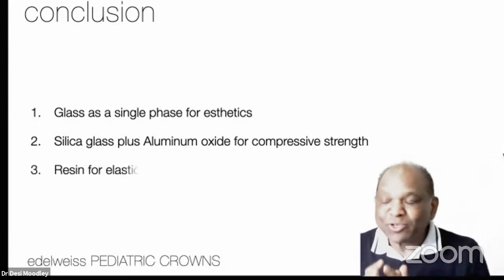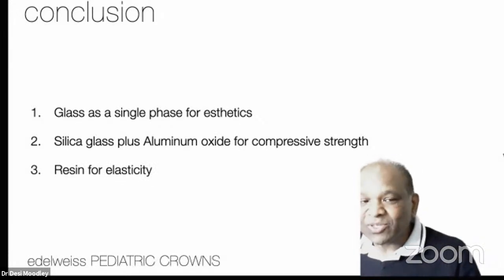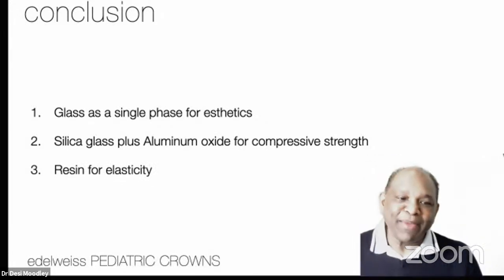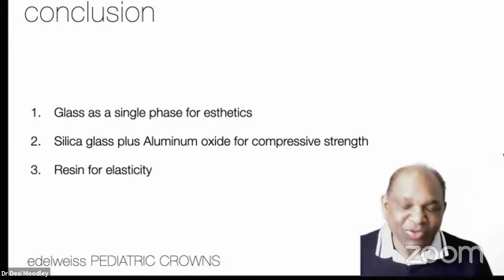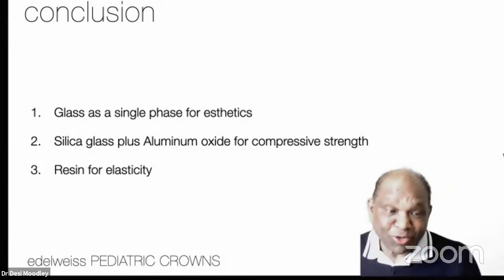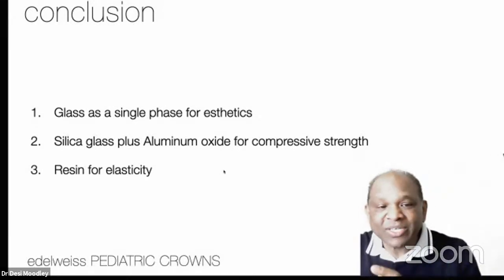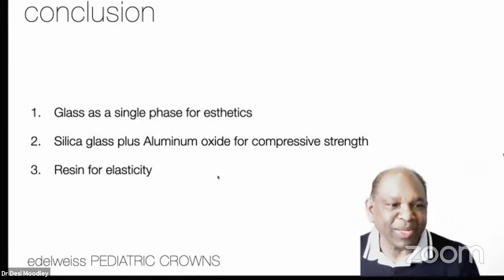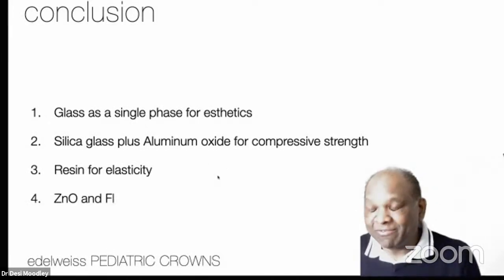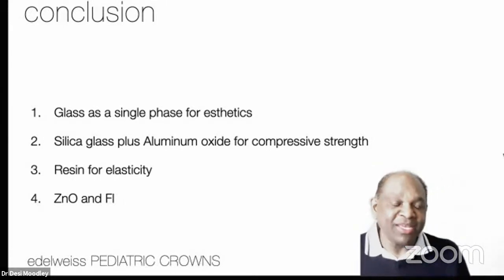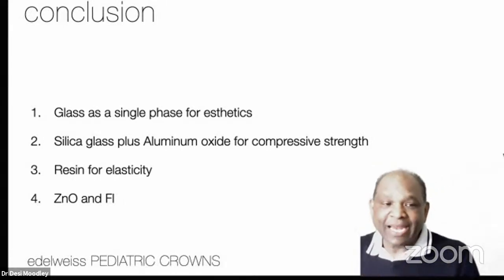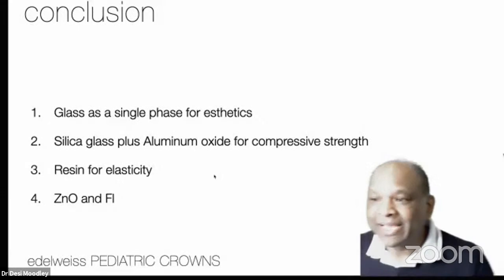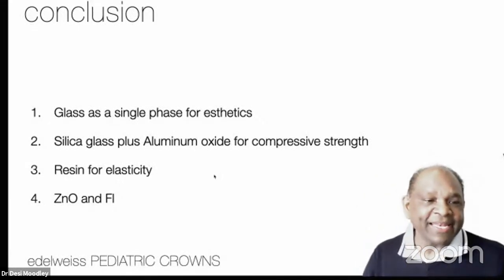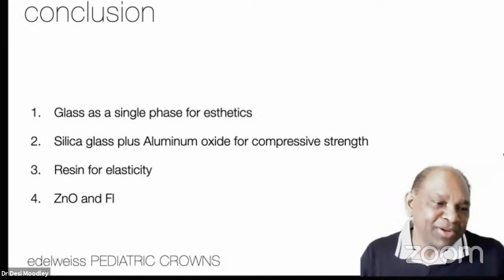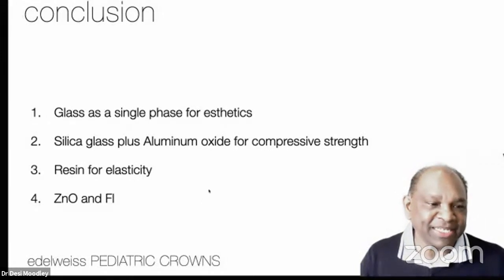But at the same time, you still have some resin for some resilience or elasticity. So you could repair in the mouth or you can adjust in the mouth. So it makes it much easier for you to place this crown and also to adjust, and you can make it into veneers as well. And then finally, of course, and very important to me, you have the zinc oxide nanoparticles as well as the fluoride. And this is quite important, especially with pediatric cases.